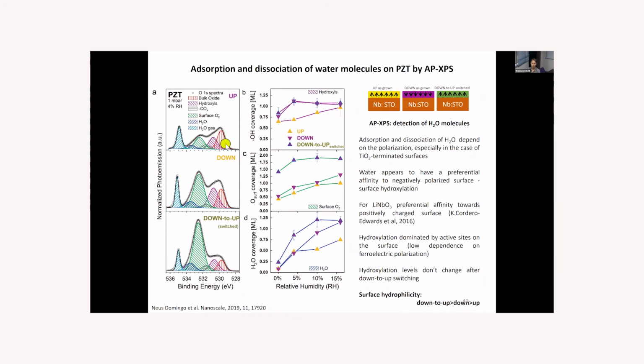This is the bulk oxide peak in red, hydroxyl groups in purple. Then we have carbonates and surface oxygen, what's called the surface oxygen peak. And it's still not really clear what this peak is. And also the adsorbed water molecules. So we could see that for the down and down to up switched surfaces, the adsorption and dissociation of water appears to be preferential. And the surface hydroxylation also is higher, especially for the down polarized sample.